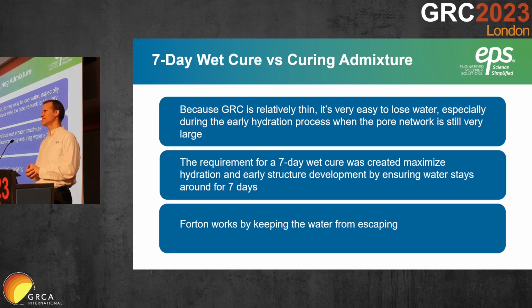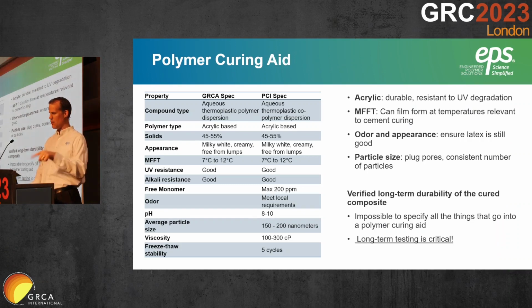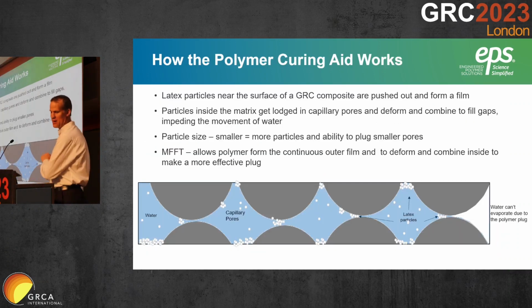Shortly after alkali-resistant glass fiber came to be a thing, Forton was also added into the mix and was shown that by adding 5% of that by weight of cement, you could eliminate the need for the 7-day wet cure. How does that happen? It's a somewhat complicated process, and honestly, we don't understand it perfectly. But in general, it works by keeping the water from escaping the system. I will come back to this. I put them out of order.